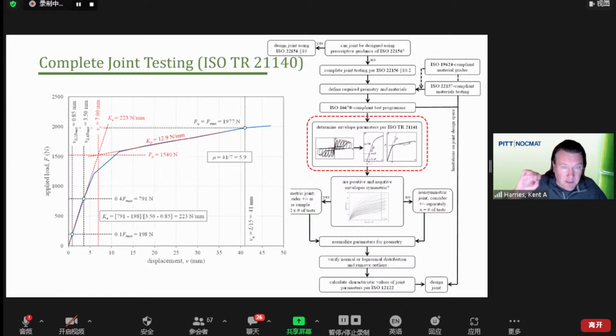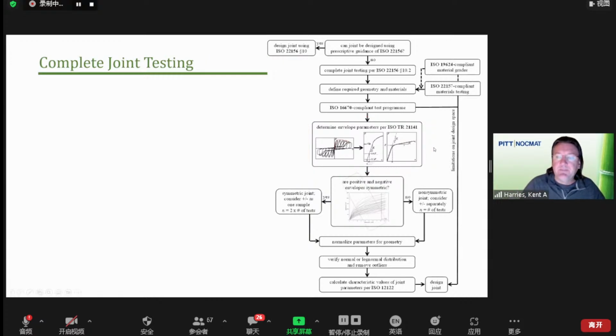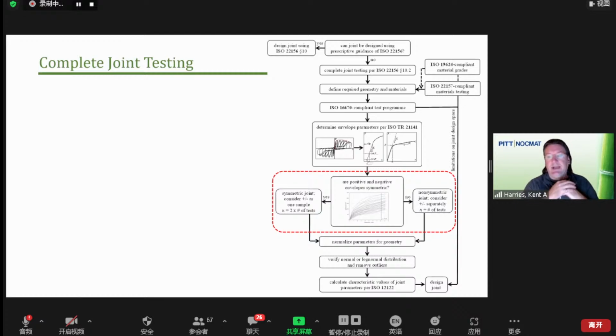Now, keep in mind, I've got 20 tests. I've got 40 backbone curves, 20 positive, 20 negative. And that brings up the next question. I need to look at my data and determine, first of all, does it make sense? But secondly, in my particular case, this particular joint would be expected to behave symmetrically, where positive and negative behavior would be the same. If that's the case, we actually have 40 backbone curves. You could also imagine a joint geometry which is non-symmetric, where it's going to have a very different positive and negative capacity.